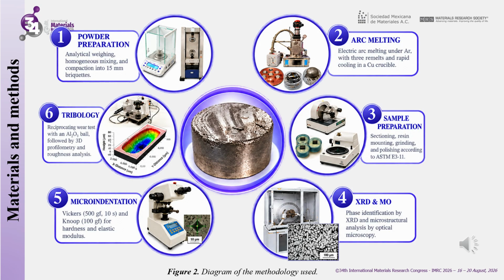As for materials and methods, the alloys were designed with a base composition of titanium, niobium, hafnium, and copper, using powders of titanium, niobium, hafnium, and copper. In the formulation, the niobium content was maintained at a constant 25% by weight, while the hafnium content was set at 16% by weight. The copper content, on the other hand, exhibited a range between 0% and 7% by weight, with the remaining balance being attributed to titanium. The powders were weighed using a precision analytical balance and subsequently mixed to ensure homogeneity. Subsequently, the material was compressed in briquettes measuring 15 mm in diameter, utilizing a stainless steel die.